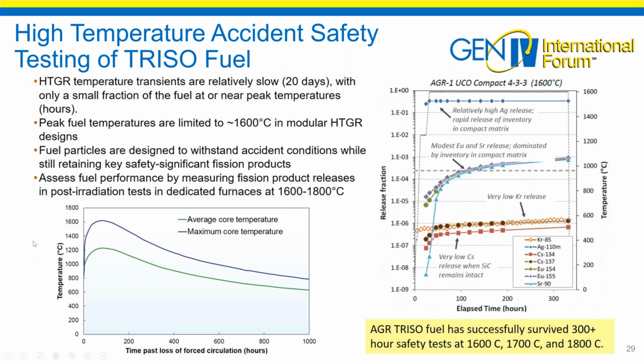So the fuel particles have to be designed to withstand accident conditions and retain the significant fission products. So we're going to assess these by doing dedicated testing in furnaces between 1600 and 1800 C. We basically have 2 sets of furnaces to do this in. And I just have one representative compact here. It's a 1600 C test. And what's important here is that our fuel has very low cesium release when the silicon carbide layer remains intact. There's low krypton release. Remember, krypton's a noble gas, so it won't react with anything, so it will go out.